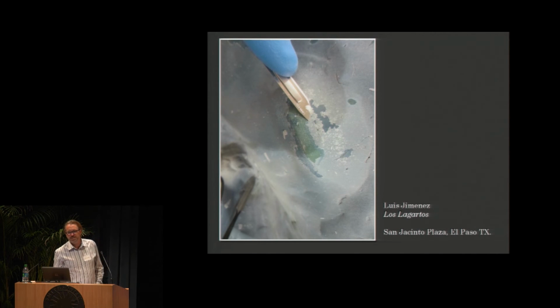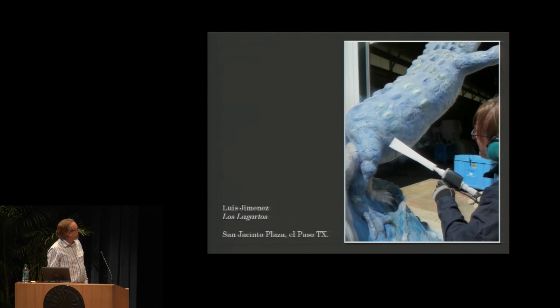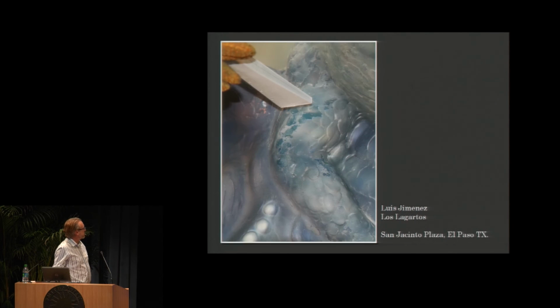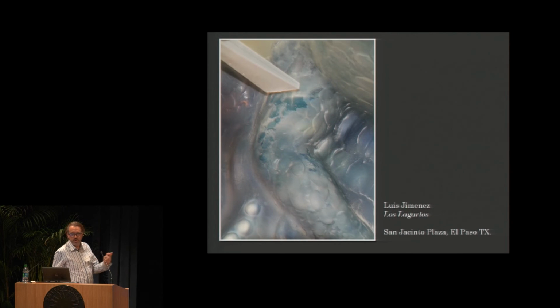Faced with having to use a scalpel for like a year, I figured there had to be a better way. So this is actually the reason why we bought this machine. So I started testing with dry ice, and I was able to surgically remove the harder top coat from the softer base coat. It had to do with technique, but as you can see, it was quite effective at removing that hardened top coat and leaving the softer base coat behind. So I was pretty happy about that. That took me 3 days to do the whole sculpture.